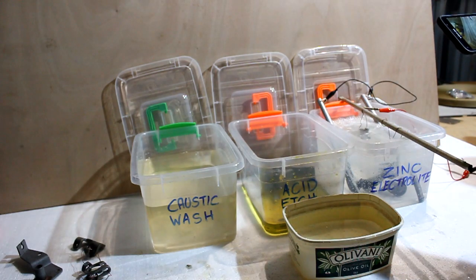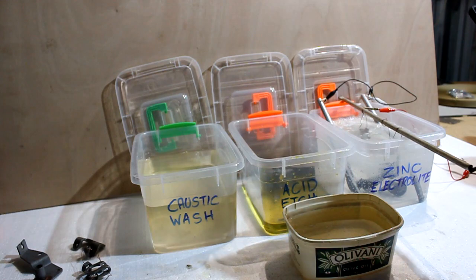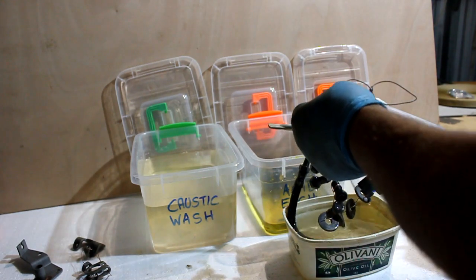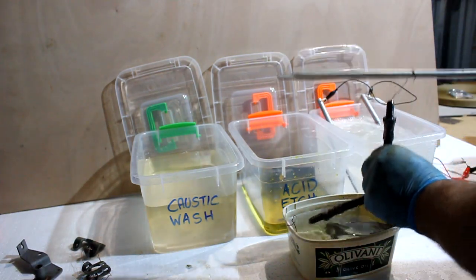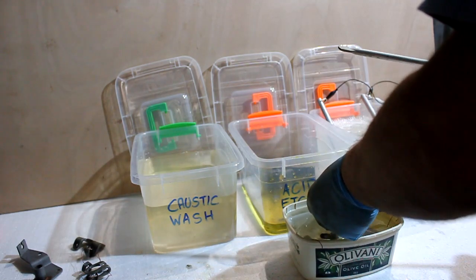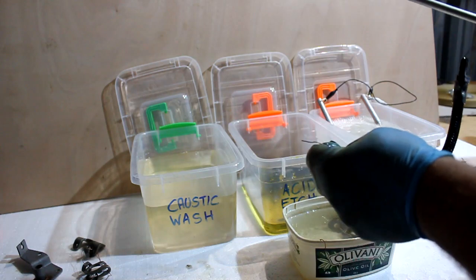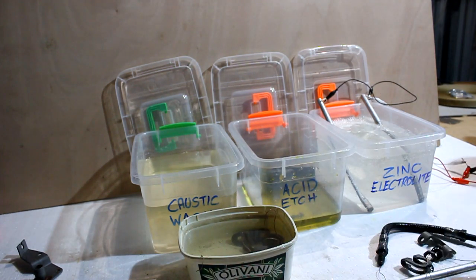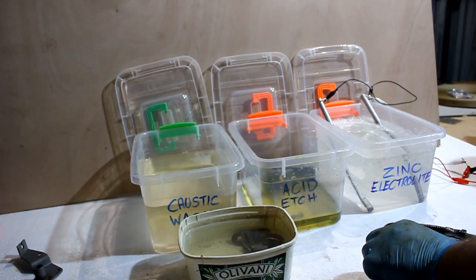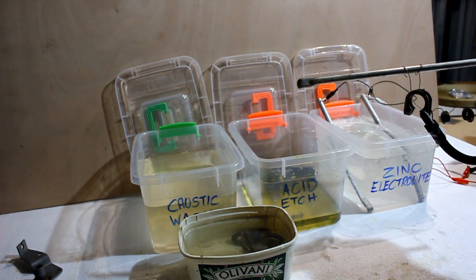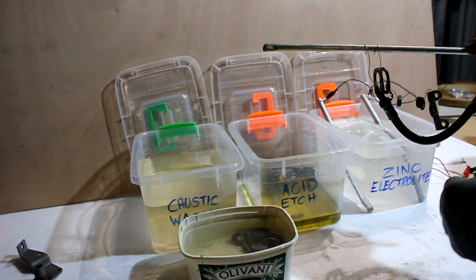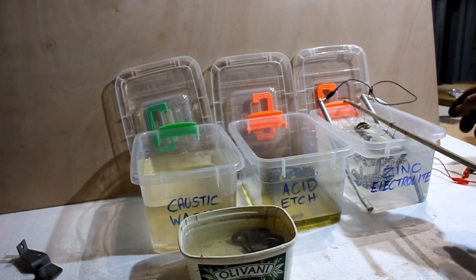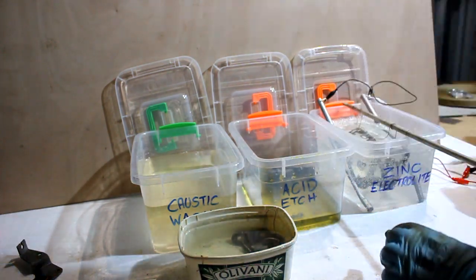So I'm going to take these first parts out now and string up some of the next parts. I'll put the brake hose back in because that's only been going for a short time. I'm finding out that it's important to move things around so that they get an even coating. I think it's important to separate parts so that they don't sit together. Okay, the parts are all separated. Make sure that everything is submerged and we'll hit the go button again.